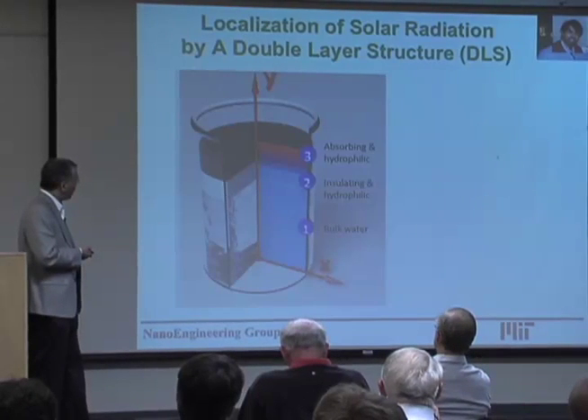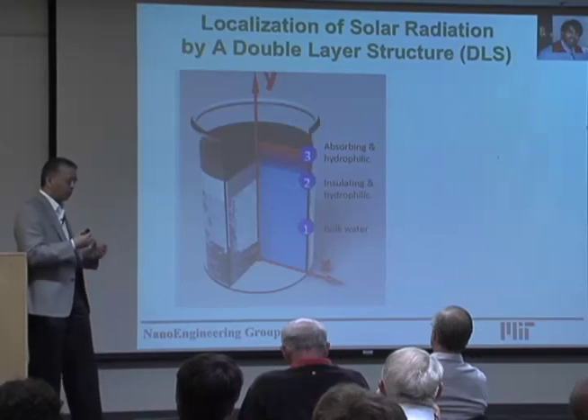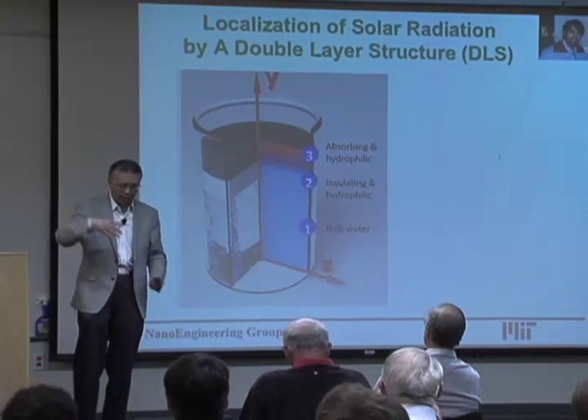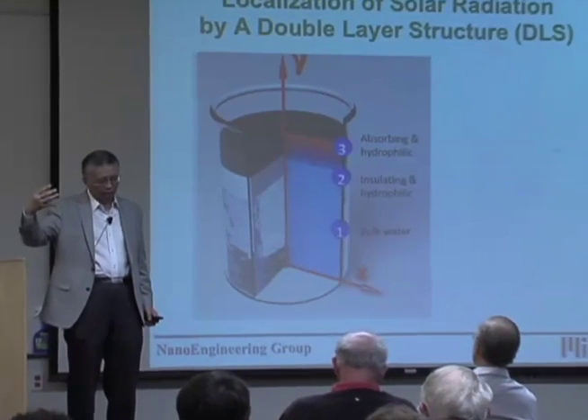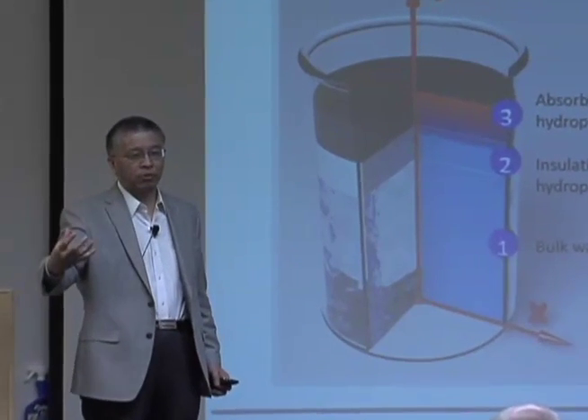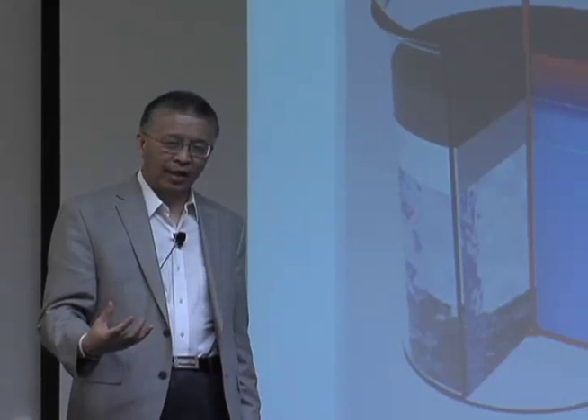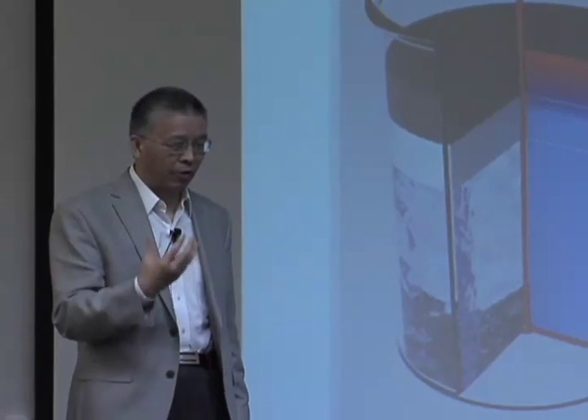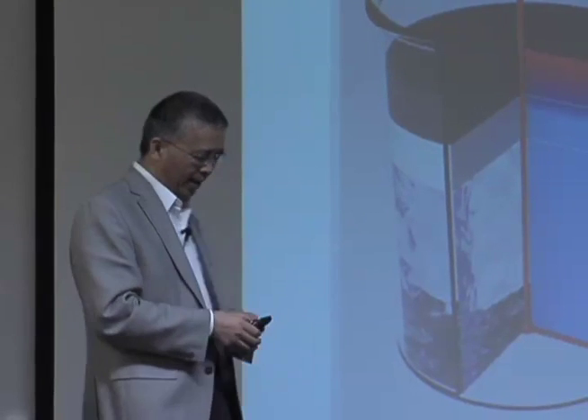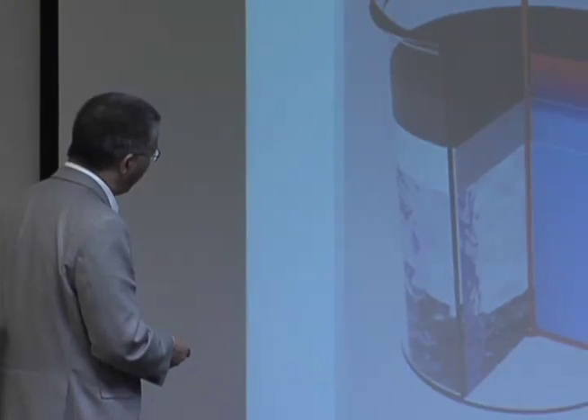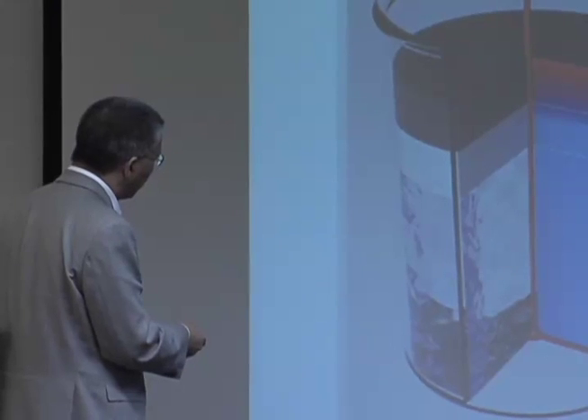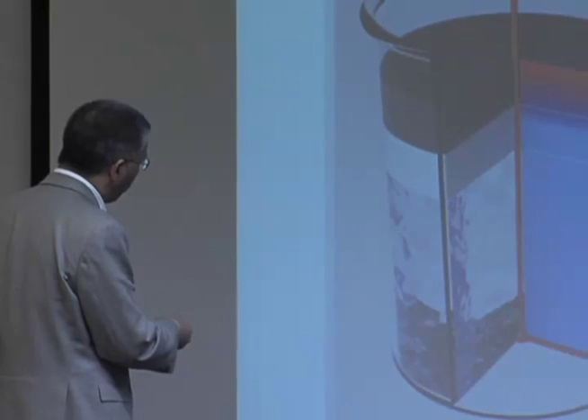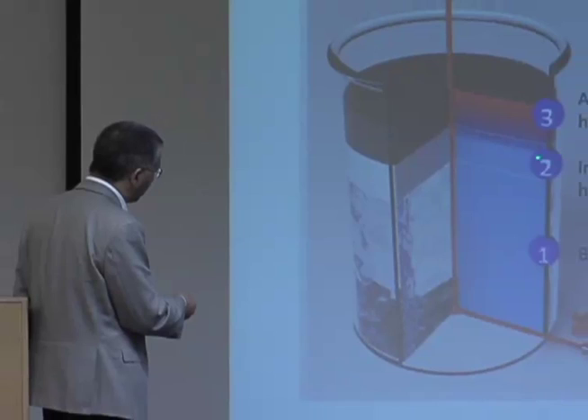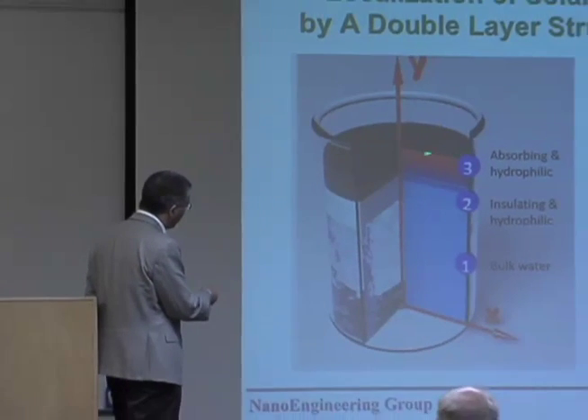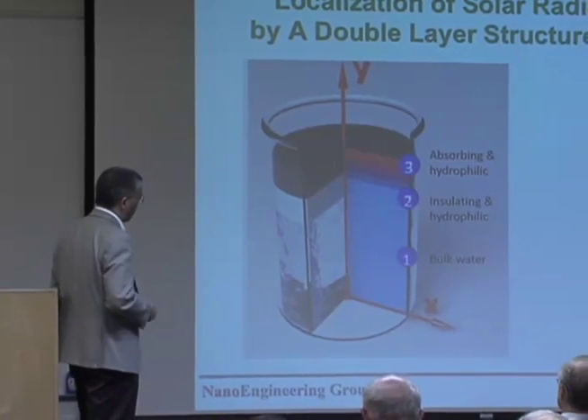So we came up with the idea of local heating. Basically, what Naomi Halas was doing is using nanoparticles to absorb solar radiation, generating a local heat source. So the question is, what's a good way to generate a local heat source? We used this two-layer structure. Here is a thermally insulating layer, here is an absorbing layer, and here is water.